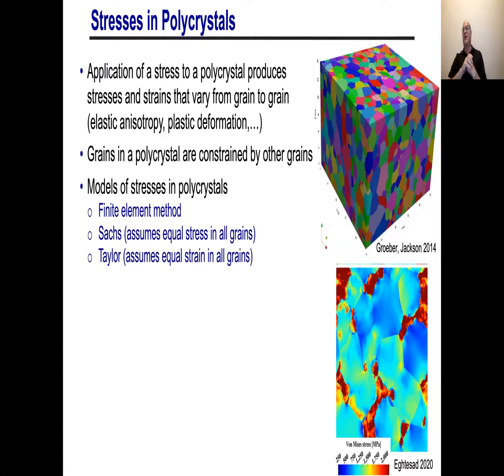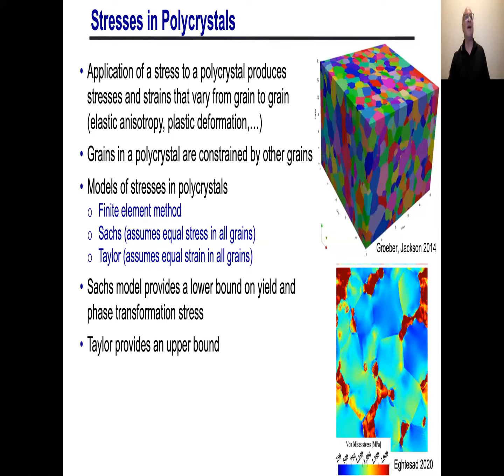Well, we're going to cheat a little bit. If I have a good constitutive law, I can just do a finite element calculation and get all this variation. On the other hand, I can get bounds on the problem. There's the Sachs bound and the Taylor bound. One basically assumes that all grains of the crystal are under the same stress. That's Sachs, and Taylor tells us all grains of the polycrystal are under the same strain. Neither one is right, but those are the limits. Those are the bounds. So the Sachs model provides a lower bound, and the Taylor model provides an upper bound. Okay, and that's a rigorous statement.